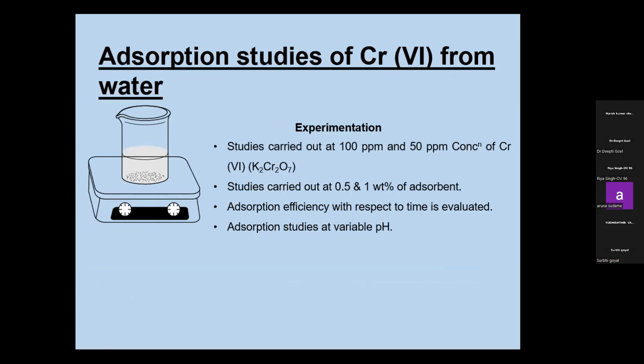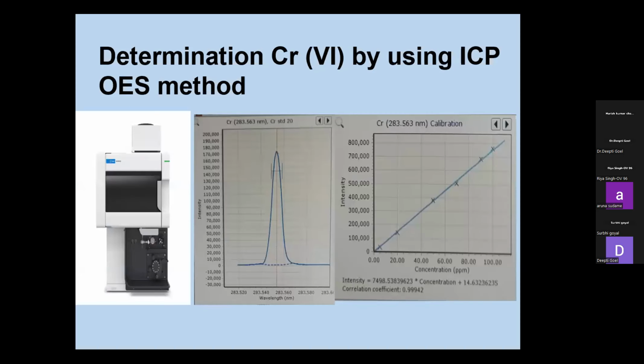Now here is a study which is going on, and chromium 6 is taken as the element. The experimentation is carried out with 100 ppm and 50 ppm concentrations of chromium which are prepared, and the experiment is done with 0.5% and 1% weight of adsorbent. Adsorption efficiency with respect to time is evaluated. Of the 2 to 3 parameters evaluated, one is the adsorption efficiency with time, and another is the pH. Now this is a result which is obtained with the help of OES, that is, inductively coupled plasma optical emission spectrometer, and this is a standard graph which is obtained here.